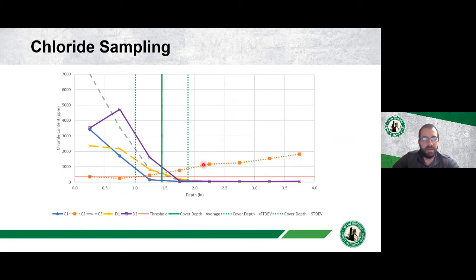This line here, you can see that increases with depth. This is an oddball. This is most likely what is happening near a crack or some other kind of construction joint where chlorides are kind of getting deep into the structure or moving horizontally water from somewhere else. And so that's an indication that there may be cracking or a construction joint or some weird defect that's not allowing the proper transport of the chlorides.